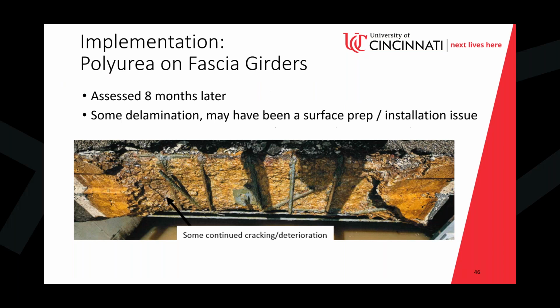This is showing that area, just looking at it later. There's an area pointed to on the left where there seems to be a little bit of delamination. So maybe we didn't clean off the surface well enough to get to sound enough concrete, or we didn't apply a second coat of one of the primers because of the time issue. We actually ran out of time in the day. And so, you know, having another coat may have helped to prevent that.